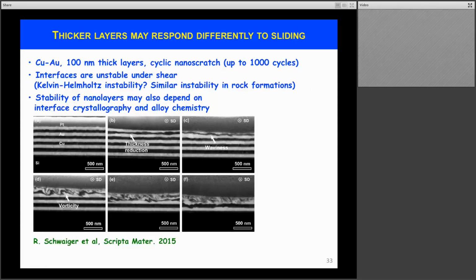And so not all layers, however, are equal, and there's work that I borrowed from the literature showing that thicker layers of copper and gold may respond differently. In this case, you see the evolution of layers that are more like 100 nanometers thick, and the response is different. They develop instabilities that are possibly driven by a Kelvin-Helmholtz instability, also reminiscent of reactions seen in rock formation. These instabilities have been reported quite a while ago in the literature. I borrowed this picture from a paper by Suh from the mid-70s, already showing unstable mixing at interfaces under sliding wear.